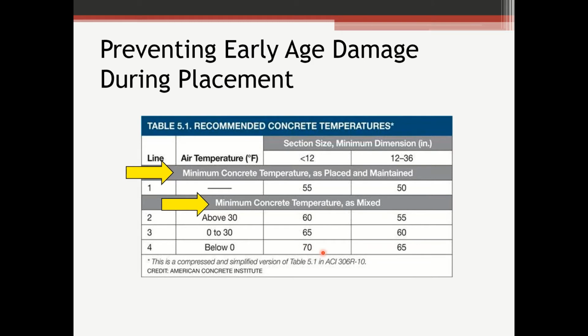This is where that 15 degree maximum comes in. It's not listed in this table, but it is mentioned. You don't want to heat the concrete up to 100 degrees just because it's cold outside. That could cause other problems. So the recommendation in 306 is to mix within 15 degrees of this, or no more than 15 degrees higher than these temperatures, or these if you're in these larger sections.